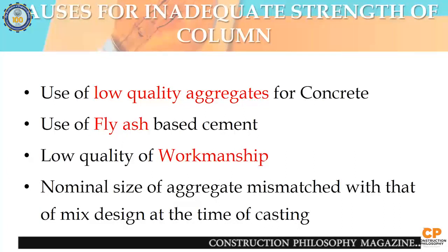So there was a lot of study, a lot of arguments on how to find out, and I should remind you that the project was executed by one of the biggest contractors in India, and the quality control was done by an internationally acclaimed PMC. So again, low quality aggregate for concrete was suspected. Fly ash based cement, the type of cement was changed, again redone, the testing was done. Low quality of workmanship, every point including the point where the loading was happening, was checked, cross verified. Nominal size of aggregate mismatched with that of the mix design at the time of casting, that also was cross verified.